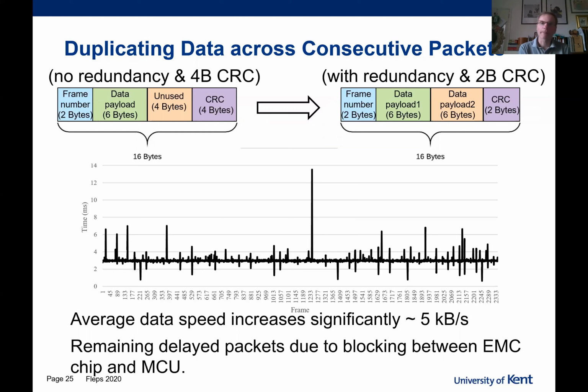So we now have 2 data payloads in the packet, both of them 6 bytes, to fit within the total 16 bytes. That means we have to reduce the error correction at the tail of the packet to just 2 bytes. The first payload we can regard as this cycle's data, and the second payload is the previous cycle's data, which is being resent. So every payload gets sent twice, and that redundancy almost always prevents the need to use 2 cycles to send data.